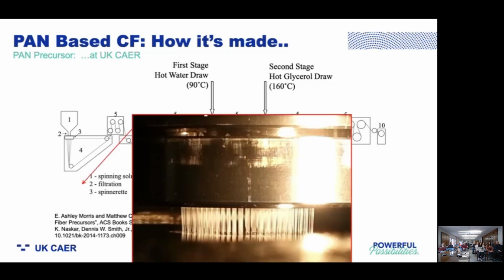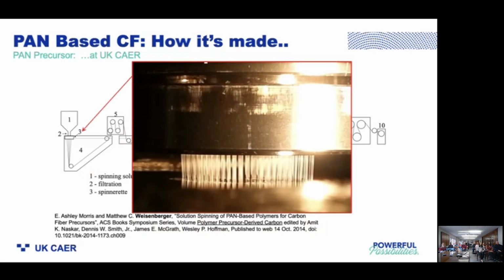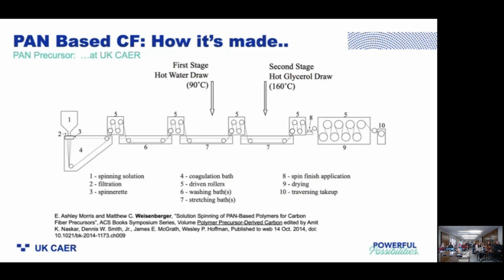It involves extruding the filaments through a shower head of holes through an air gap, about 1 centimeter, and then accelerating those filaments down into a liquid bath. The solvent diffuses into the liquid bath, which contains water. Water diffuses into the forming nascent filaments and precipitates that into solid polyacrylonitrile. This then goes down the spin line to be washed and stretched. We stretch it in boiling water or really hot water, and then stretched again in hot glycerol to get the temperature up a little bit higher above the glass transition. Then we apply a spin finish, dry the fibers, and take those up.